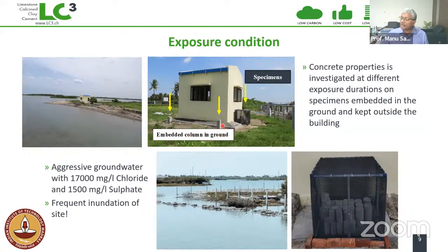You can see that we have embedded some columns in the ground for a long-term study about how the concrete deteriorates. Even these embedded columns are structural reinforced concrete, so we can understand whether corrosion is happening or not. We also have concrete specimens that have been stored alongside after 7 days of curing. And we are taking specimens from here, bringing them to the lab and testing them from time to time.